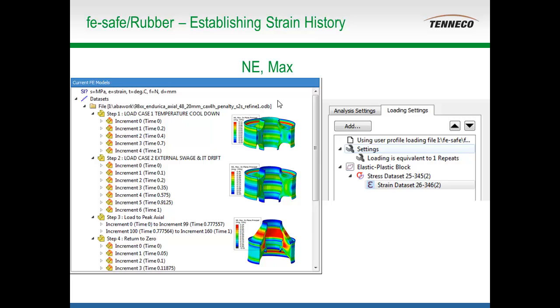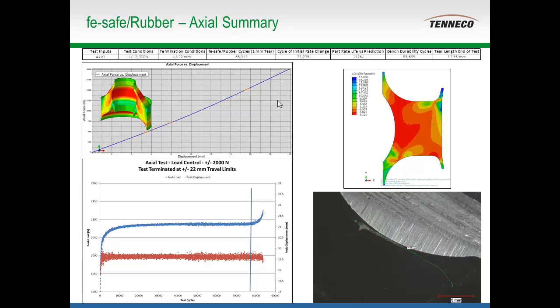You kind of hurried through some of the last few slides, but I just want to make sure you had a chance to flag up, not only did you get the lives within 1.4, which I was quite delighted to see. I'm used to seeing, you know, that's a really good. But obviously, you guys have done a lot of work around being very careful to characterize and being in control of your experiments, so I'm sure that had part of it. But I also wanted to make sure you didn't blow by too fast in comparing the pictures that you got of the initial crack to the predicted crack locations.